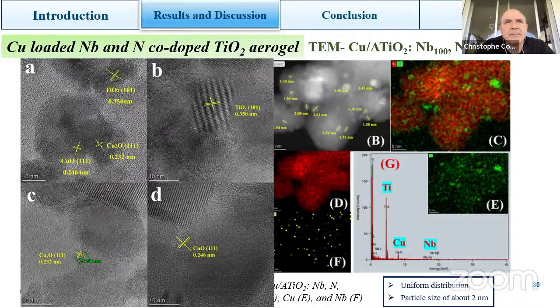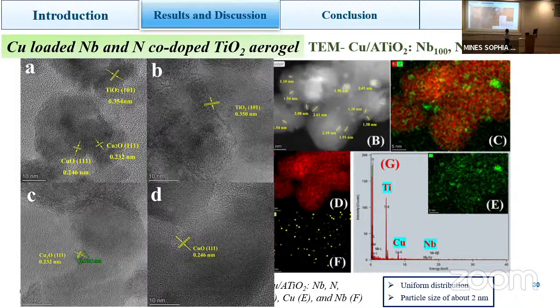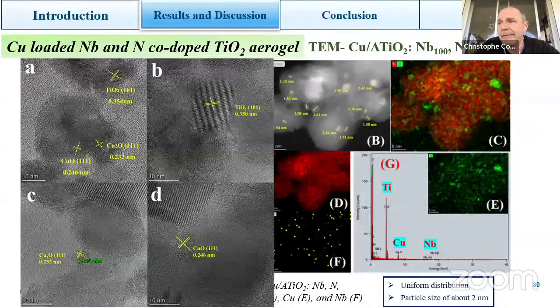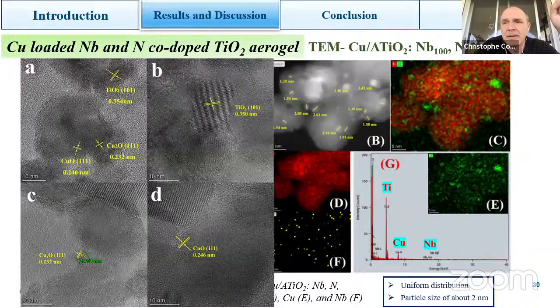Okay, because the idea is to try to understand the mechanism of your CO2 reduction. When you run the photoactivity, you are illuminating your titanium dioxide. We are creating charge carriers, electron and hole, going to the surface and generating some reduction and some oxidation. So you need to reduce your carbon dioxide to produce methanol.